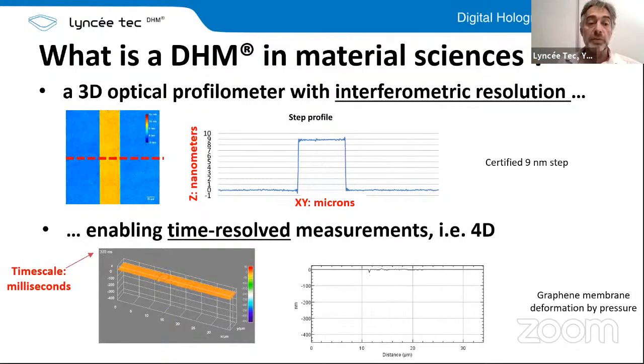We can make 4D, and you can see this is a graphene membrane deformation due to a differential pressure between the top and the bottom. The time scale is milliseconds. So a standard system measures at 200 frames per second, but we also use a high-speed camera to measure up to 100,000 frames per second full frame. So we are very, very fast.